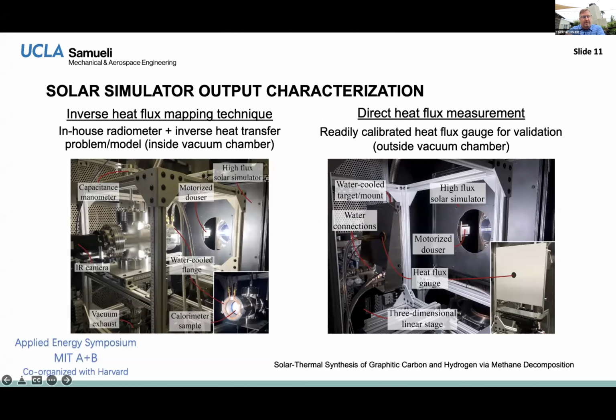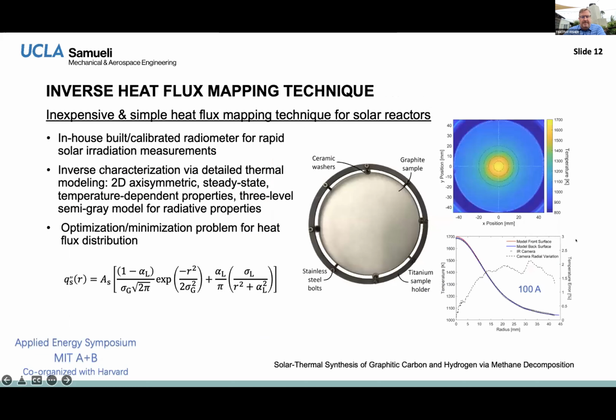Again, I think one of the things we had to do, because we hand built this, was to characterize the actual optical output. And so I'm going to show a couple of slides about that. We did it in 2 ways. Well, really 3. Modeling was the third. But we built a radiometer and used an inverse heat transfer problem solution to determine the distribution of intensity at our focal point on the receiver side. But we also did direct heat flux measurements. That's what's on the right, using a Lambertian target. And so here's the inverse problem, right? And it's important to note, you're going to see this a lot in the talk.